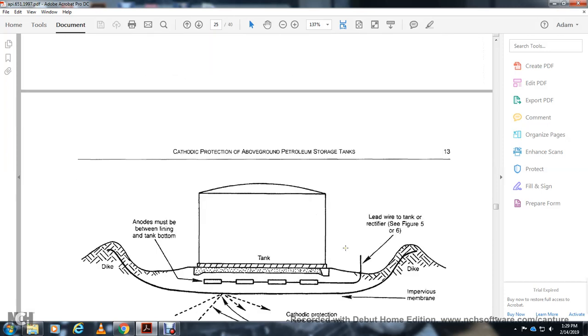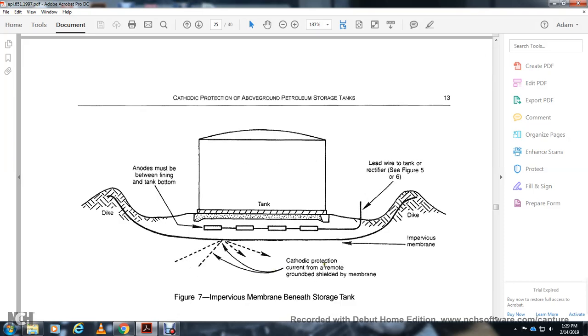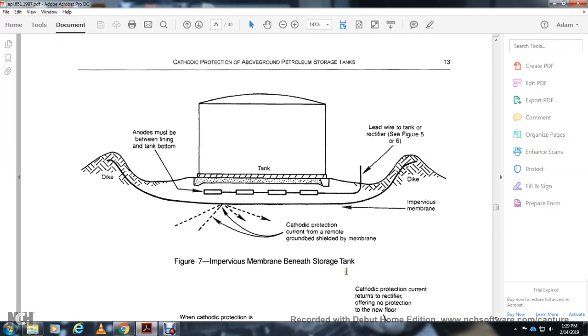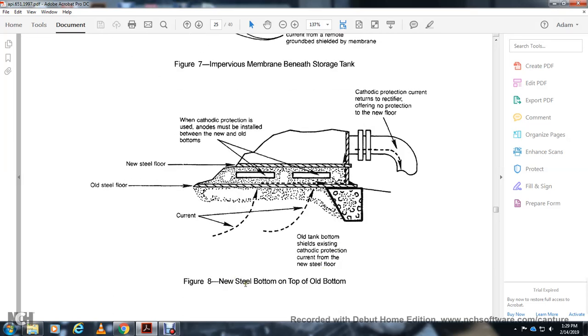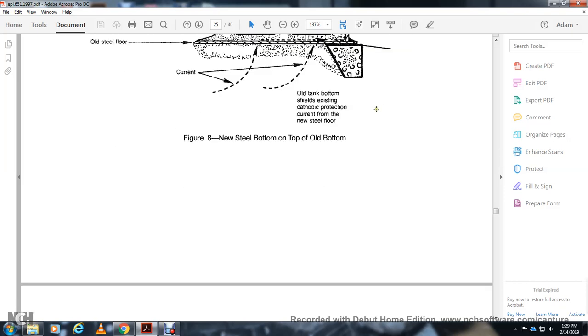And then it showed the anode must be between the liner and the tank bottom, with the wire laid to the tank and the rectifier, and the impervious membrane with the cathodic protection current from the remote ground bed shielded with the membrane. And then over here you have the new steel bottom tank with the cathodic protection anodes installed between the new and old bottom. The old steel floor shields the existing cathodic protection system from the new steel bottom, and the cathodic protection current from the rectifier offers no current, no protection to the new floor.